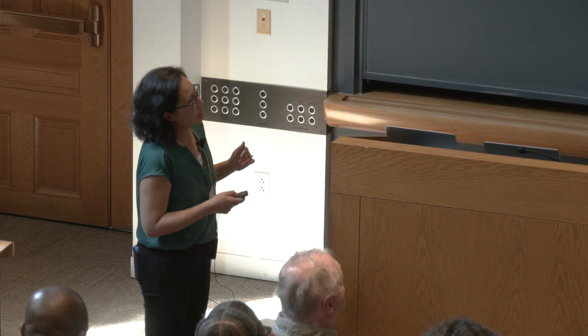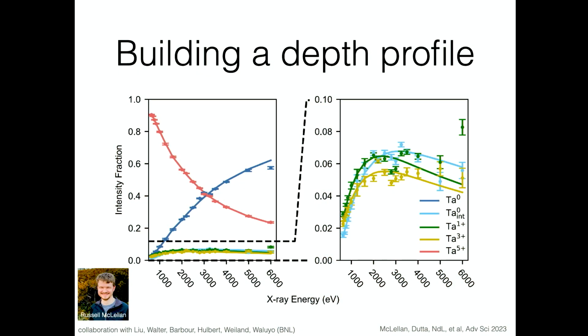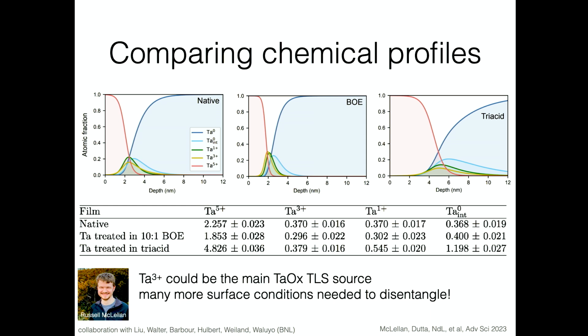Okay, so we use this to try to develop a depth profile of all of these different species. As you would expect, as you go up in energy, the tantalum oxide peak goes down and the tantalum metal peak goes up, because the oxide is sitting at the surface. And then we have all of these different stoichiometries that increase and then decrease, which means that they're sitting at some intermediate range. And then we're able to build up these profiles of these different surface conditions and come up with new hypotheses for what might be the microscopic origin of these two-level systems.